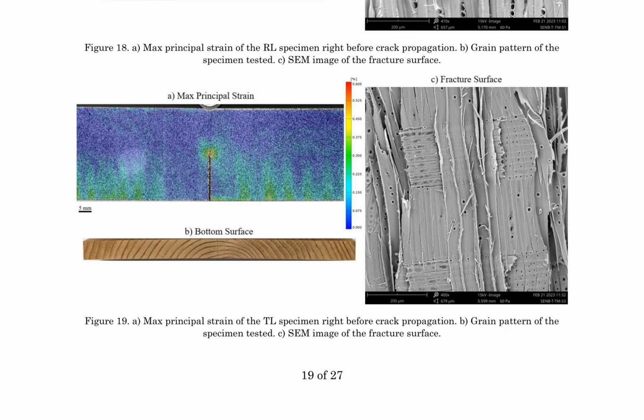Figures 18 and 19 illustrate these differences visually, showcasing the maximum principal strain distribution, grain pattern, and SEM image of the fracture surface for both RL and TL specimens. These visual aids highlight the distinct fracture behaviors between the two types of wood specimens. The research findings contribute to understanding the role of grain orientation in determining the fracture behavior of wood, with implications for optimizing wood-based materials in various engineering applications.